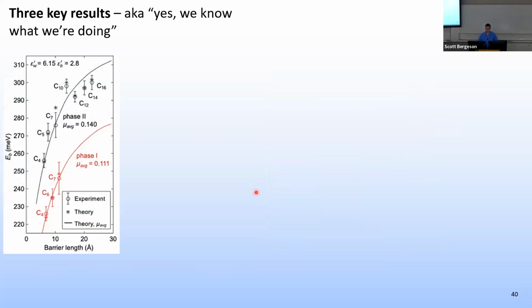But there are three key results that I want to present from this work that prove that we actually know what we're doing. So this is the same numbers that I plotted before, the dependence of the binding energy on barrier length, where you can see for short barriers, you get a really small binding energy. Well, using this theoretical framework from the 80s and 90s, we could deduce what the well and barrier dielectric constants needed to be, and then use those in the theory with the effective mass from some other theory, and almost get an exact match. This one here was problematic, but the experiments are the open circles, the theory are the asterisks.